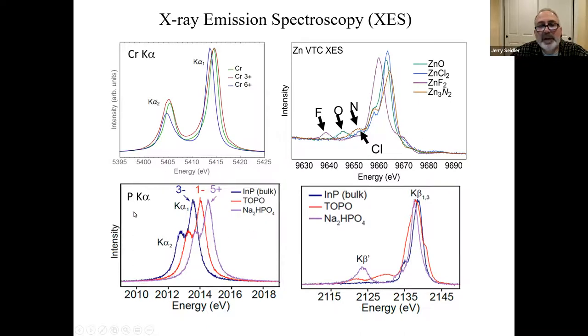Down at the bottom, for lighter elements, the shift in the K alpha is often much simpler. You can see here what's happening with phosphorus going from plus 5 to minus 3. And the valence-to-core can really be quite rich, with an awful lot of spectral information about chemical bonding.